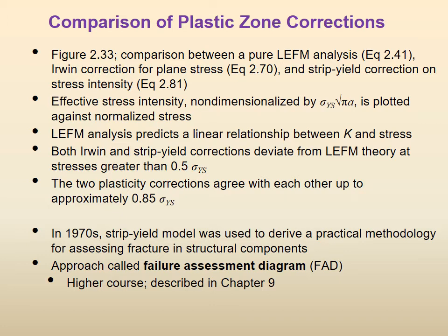Just like strain is inch per inch or meter per meter, it is the same value because it is just a number. So we take the effective stress intensity divided by sigma root pi a, in megapascal root meter. So now the number is non-dimensionalized, and therefore we can use it for any system of units. This is what they are saying. Now, in that figure, the LEFM analysis predicts a linear relationship between K and stress. That is why it is LEFM, linear elastic fracture mechanics: between the stress intensity and stress there is a linear relationship.